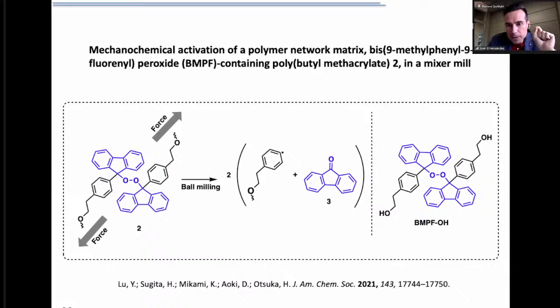Important here, the authors demonstrated the importance of the polymer, because when they tried to activate the model compound, the monomer, the diol, which lacks the polymer, the efficiency was really, really poor, meaning that you really need the polymer to use that mechanical force that you achieve by ball milling in order to activate the mechanophore. Also, the polymer and also the monomer are stable at high temperature, meaning that the reaction was mostly mechanochemically driven and not thermally driven. So here we have examples in which a technique, ball milling, which is often used for small molecule mechanochemistry, can also be applied for the activation of mechanophores in polymer mechanochemistry.